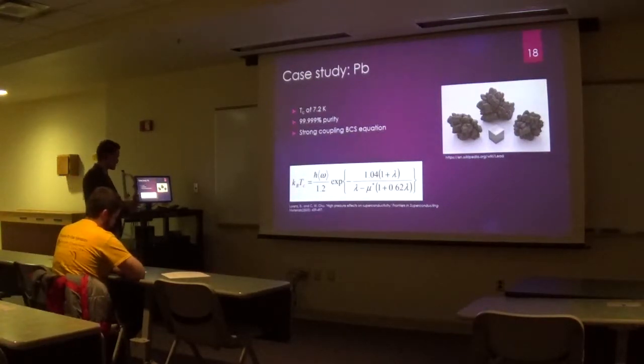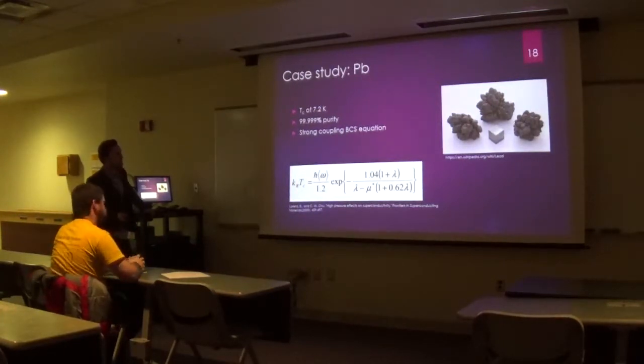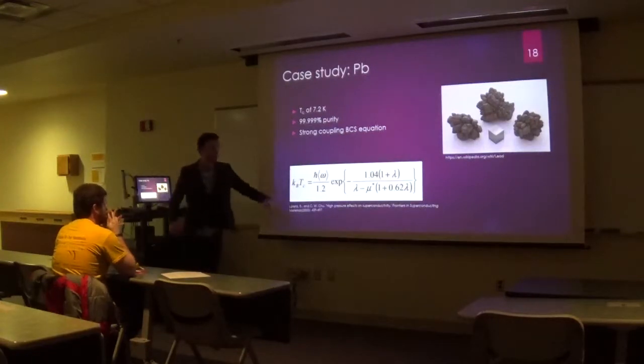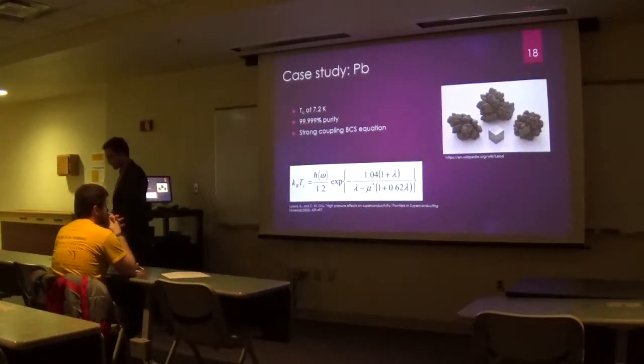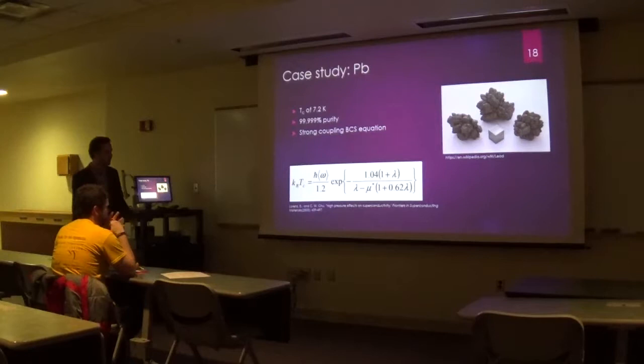So to measure how pressure affects our critical temperature in a theoretical way, we have to use what's called the strong coupling BCS equation. Strong coupling refers to our strong coupling between our electrons and phonons in the formation of Cooper pairs. There is a weak coupling BCS equation that's a lot simpler than this, but it only works for aluminum, because it has weak electron-phonon coupling.